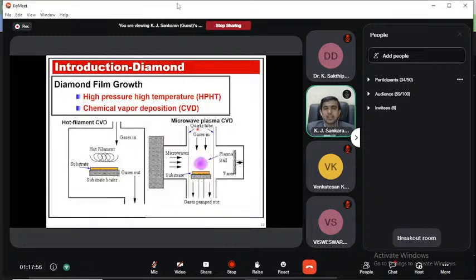Several CVD techniques were developed by the Russians as well as the US people, and one of them is the hot filament. But the drawback of the hot filament is that it needs to reach more than 2000 degrees Celsius, and the filament breaks at some point, so the growth is not carried out uniformly. Then in the 1970s or 1980s, microwave plasma CVD came from the Russian group, and the US people also developed microwave plasma CVD. There we create the plasma using microwave.